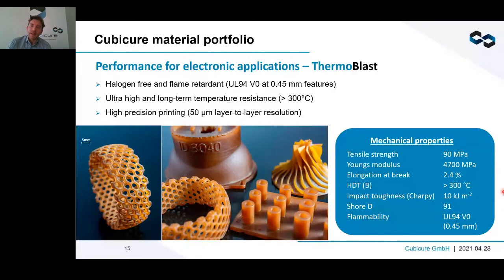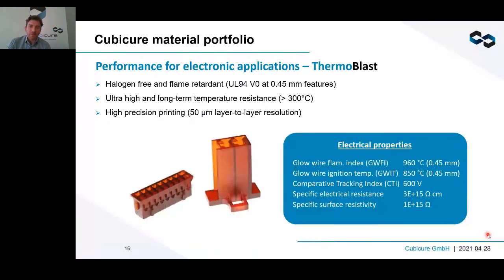injection molding. And the second most important value is the flame retardancy. Really, this goes down to very thin walls. So this is completely new to the AM industry. This is even a benchmark for the traditional polymer industry. So 0.45 millimeter wall thicknesses, which are still flame retardant. This is really a benchmark value in the whole polymer industry.